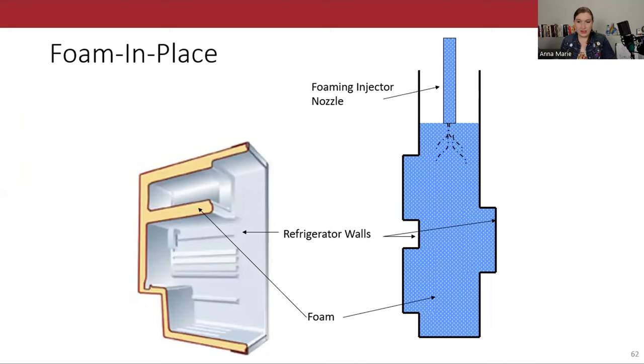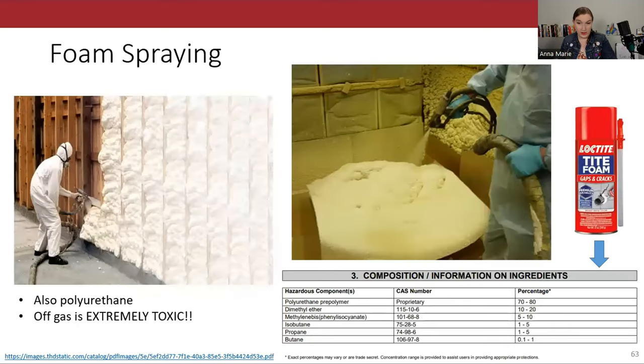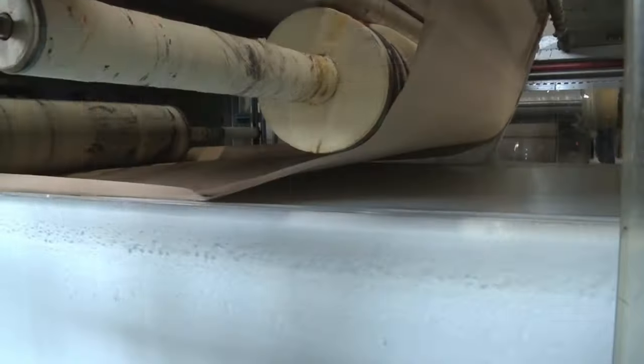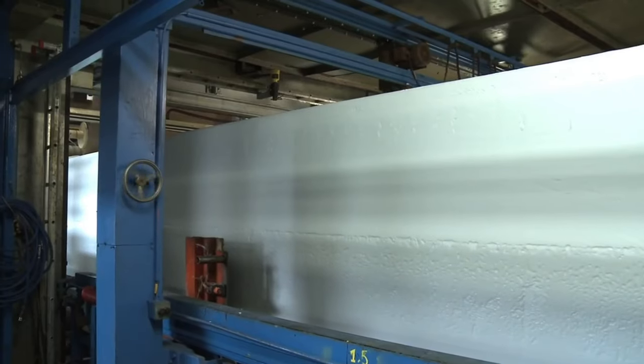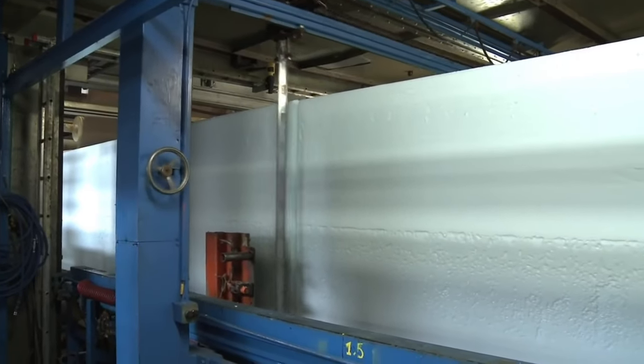This is used for super high quality, super low density materials like car spoilers or certain specialized insulation. It's also pretty common to inject or spray foam directly into where it's going to end up. For example, the insides of refrigerators contain a layer of insulation that's added by filling the interior of the fridge with the foaming ingredients and waiting. Or for home insulation, it's not uncommon for HVAC technicians to install foam with a special nozzle that mixes the polymer and foaming agents right as they exit the nozzle. Mind you, this is extremely dangerous, as are all of these foaming methods, because blowing agents are often very volatile and carcinogenic. You might also see extruded foam, where wall-sized blocks of foam are created and then trimmed down by hand or by CNC routers to get their final shape.